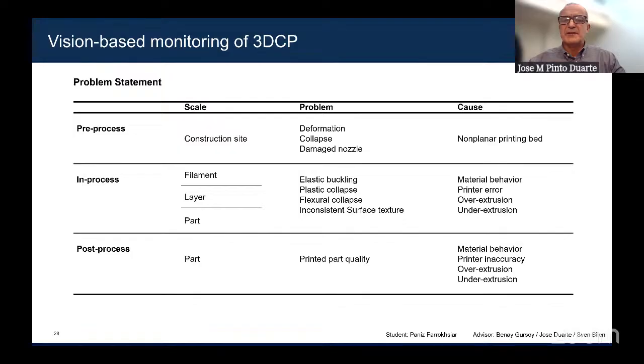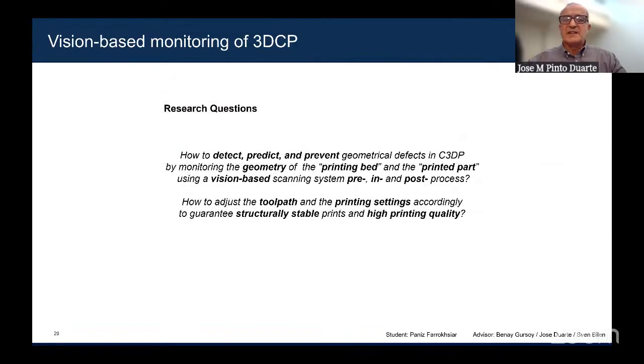And then you can use the system during printing to monitor the quality of printing, the shape of the filament, the shape of the layer, the shape of the entire part, to see if it's deforming, and if it's deforming, what might be the cause. It can lead to structural failure if you don't act. So if you follow the process this way, you can change the printing settings so that the variables remain within the acceptable and right values. And then you can also use it after you print, to compare the shape of the printed parts with the shape of the design and see if there were any deviations, to guarantee that we achieve good printing quality. So that's basically the idea.